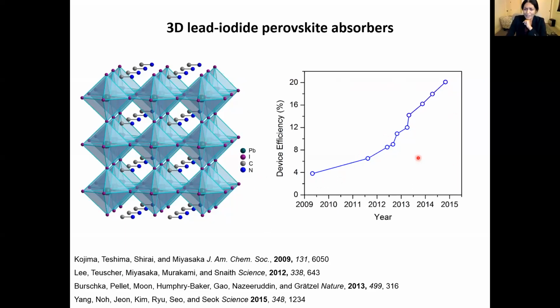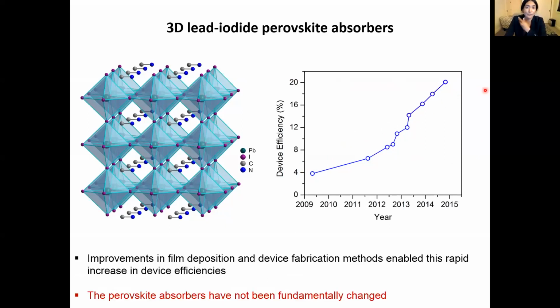So this is great. I will point out that when you see this rapidly climbing graph, you say to yourself, something's got to be changing. It turns out that what was changing was not the material itself, but various aspects of device engineering. Scientists figured out how to make better films, better layers of your photovoltaic device. The perovskite absorber that's used is still more or less the same material. So this raises the question: is this material, the very first material to be evaluated as a solar absorber, the best? Or does it have problems that we cannot address through engineering? We cannot just put a layer on top of it.